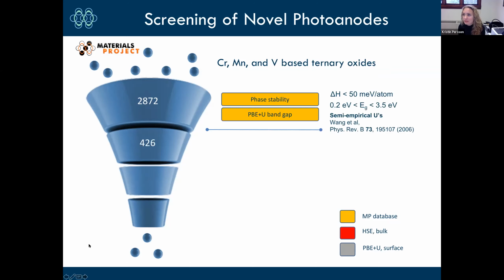You then sort or screen on phase stability and band gap, and you're using a particular functional for the band gap, so you need to be very generous. We tend to underestimate the band gap, so we're filtering between 0.2 eV and 3.5, even though we want to be between 1.1 and 2, because we know we're not very accurate on that metric when we calculate it. So we're taking a wide window of inclusive criteria here. And we're down to 400 of those materials that have potentially a good electronic structure for a good photocatalyst. Again, I haven't done a single calculation yet. This is all data that's available in the project.